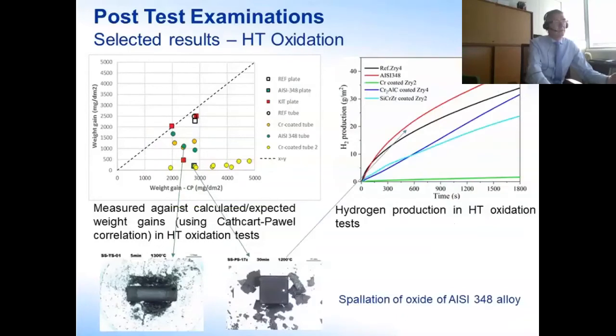Another type of test with this type of samples was high temperature oxidation, typical for accident conditions. And here again, different samples were compared. On the left-hand side graph, you can see a theoretical curve, the so-called Cathcart-Pawel correlation for high temperature oxidation, and results of testing. So naturally red is the reference samples without coating, which belongs to this line, but mainly all test samples showed much better behavior.